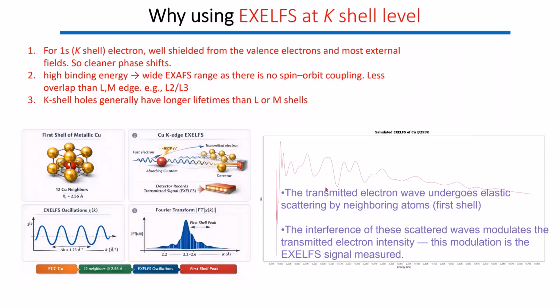And why we chose the K shell instead of the L or M shell is basically because the K shell is well shielded from valence electrons, and also pretty much shielded from the external field. So if we measure any phase shifts, that's much cleaner than the other L or M edges. For L or M edges, basically there's spin-orbit coupling, which is absent for 1s electrons, which literally means when you compare the L edge and K edge, there will be much less overlapping and it's much easier to interpret. But another reason is that K shell holes typically have a longer lifetime, which means you also have a bit more visibility for signals.